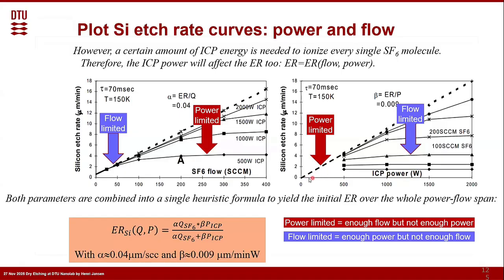Then again, in the beginning it follows that the more power you add, the more etch rate, because you have such a low power that increasing the power has a linear influence. And again, after a while it saturates, where there's just not enough flow. So in this case, this slope is flow limited, but after it saturates here, it is power limited. It's just the same. If you turn this graph around, this line is the power limited regime, and here it is the flow limited.